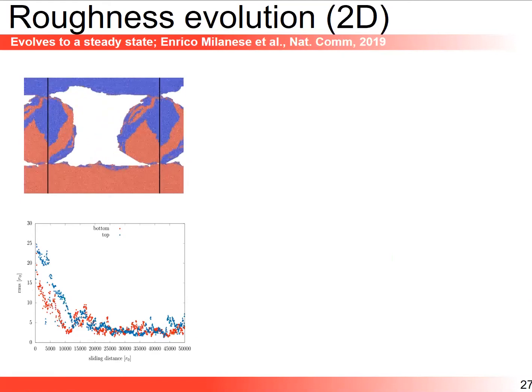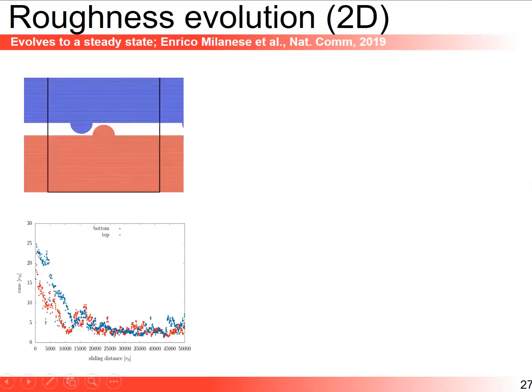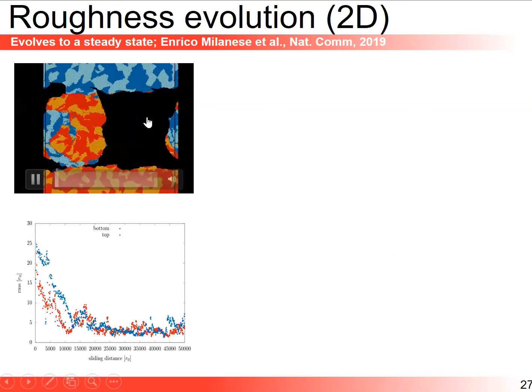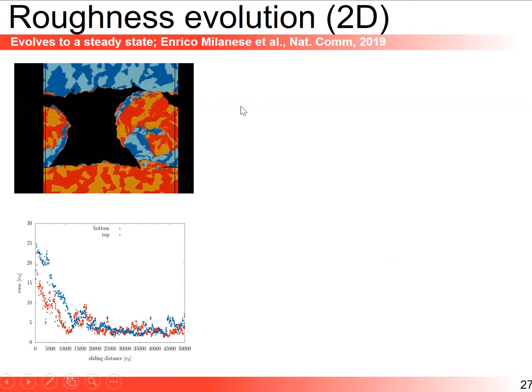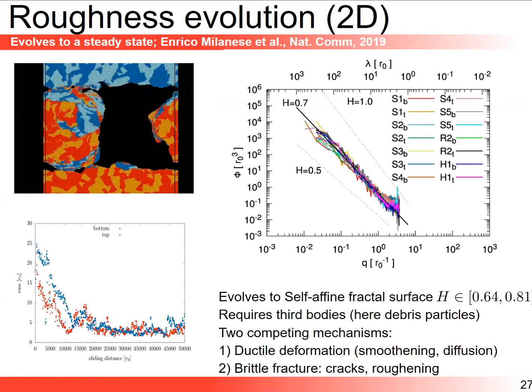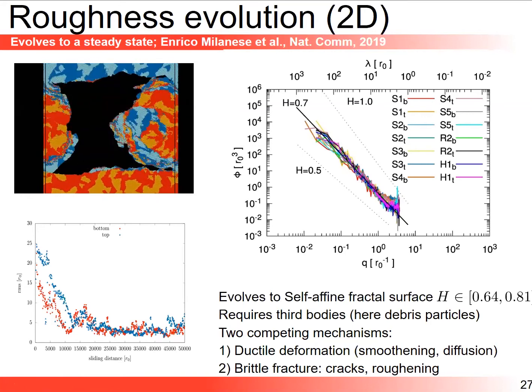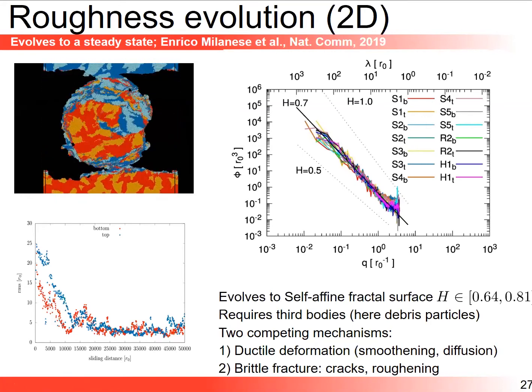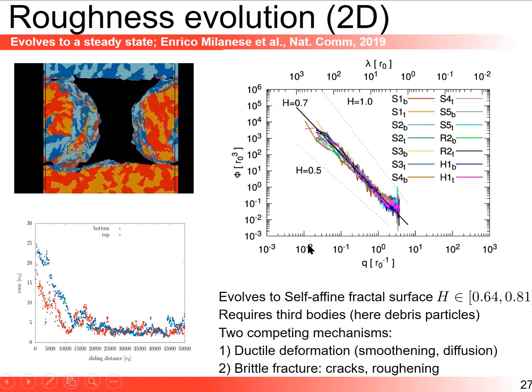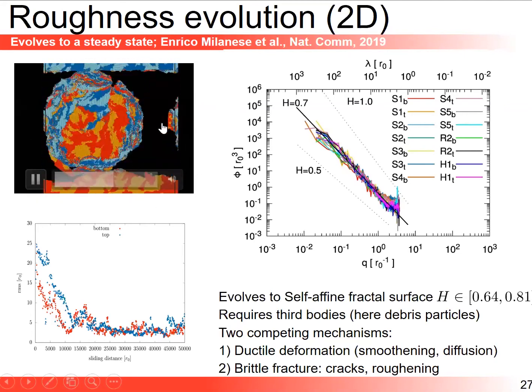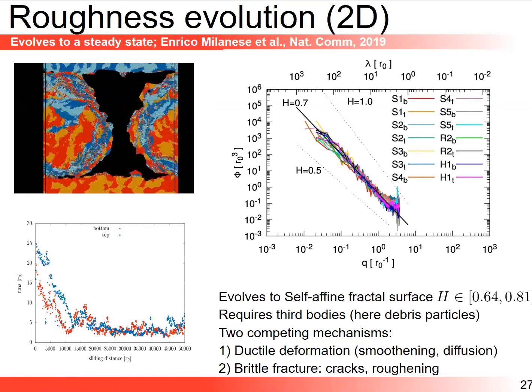And we try different systems. Some systems that were initially perfectly flat, like this one, except this little bump. We tried also systems that had initial roughness with a well-defined Hurst exponent. And we tried different mixtures of material, different colors represent different material properties. And again, here we form a debris and we develop roughness. And we've computed the PSD, the power spectral density, as I've shown you in one of the first slides of this presentation, François Renard data. And of course, here we are limited to only 2 to 3 orders of magnitude, because those are very long simulations and expensive. We cannot do 10 orders of magnitude from data directly observed on rocks, obviously.